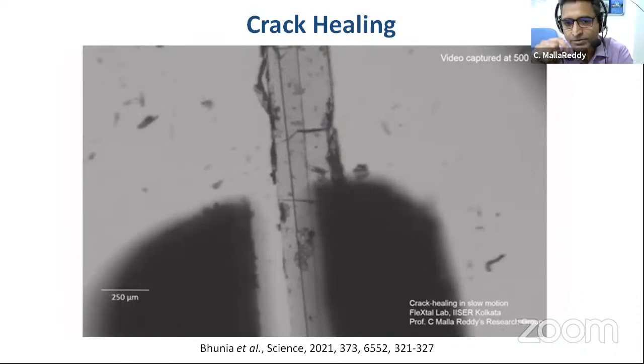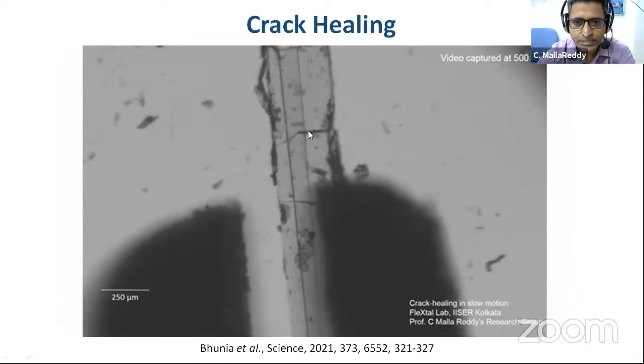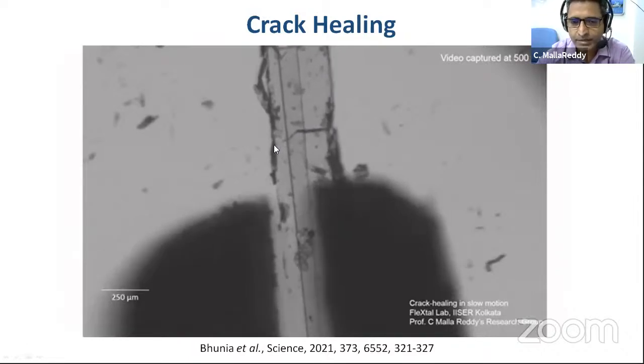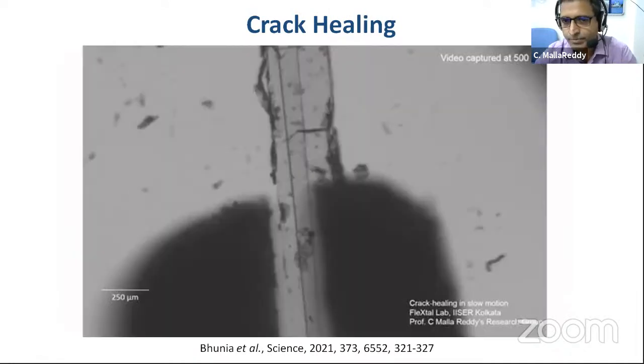But then we wanted to understand how well it is healing. So then we did different measurements. As you can see here, this crack did not heal. Most of the time, if you press very hard without a gentle push, they all break like other crystals. But then when you bring two pieces closer, they again get attached, and then they are together.